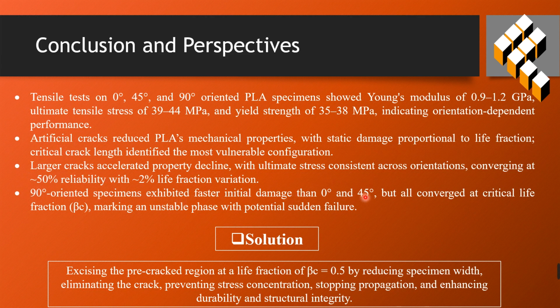As a solution, we propose that when the crack reaches 50% of its life fraction, the pre-cracked region is excised by reducing the specimen's width. This intervention eliminates the cracks, prevents the stress concentration at the crack tips, and enhances the material durability.